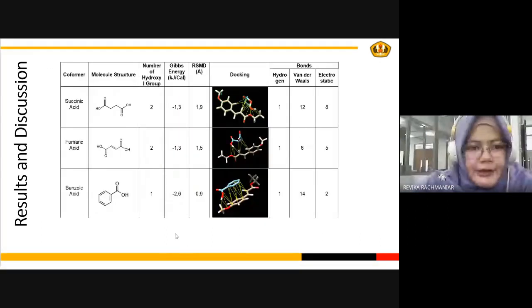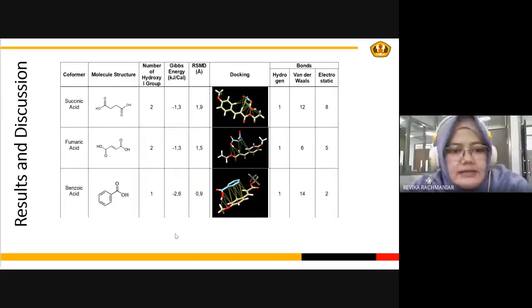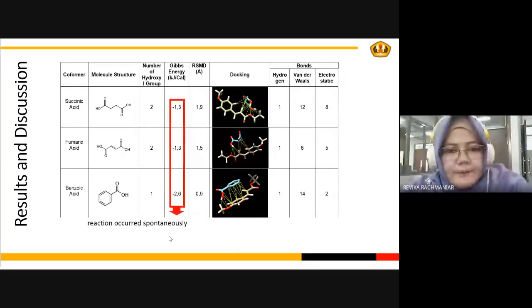The second one: there are succinic acid, fumaric acid, and benzoic acid. The succinic acid and fumaric acid have two hydroxyl groups, and benzoic acid has one hydroxyl group. The Gibbs energy between these three coformers and APMC is below 0 kilojoule per calorie. It means that the reaction occurs spontaneously.